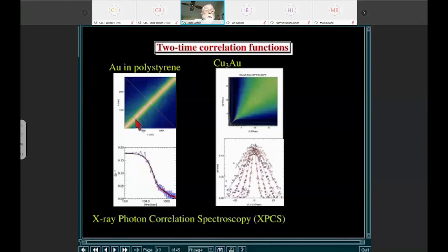And so if we see that the scattering and the two-time correlation function like this are parallel to the diagonal, we know the system is at least in steady state, and in many cases we can infer that it's actually in equilibrium. And if we take a cross-section through the diagonal there, we can see the correlation function. Here it's not exponential, but for simple diffusion it would be exponential. And that's what the blue curve is. It's just one simple plot out through this diagonal.